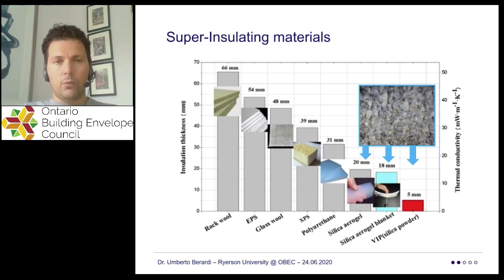So luckily for us, we have new products that are typically under the category of super insulating materials. I'm going to specifically speak today of aerogel, but there are also vacuum insulating panels that are becoming, again, more and more common for the building sector, and that often give us the opportunity to have a very low thermal conductivity. We are almost speaking about materials with a thermal conductivity of 0.01. So we are literally speaking about materials that have a thermal conductivity that is a quarter of that of fiberglass, which basically means that you can have the same thermal effect with a fraction of the insulation thickness you would have to use with a mineral material. But clearly, these new materials still have some challenges that I'm going to present to you today. So what is an aerogel?